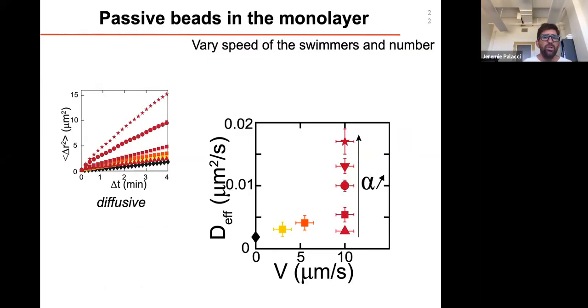So now, taking this mean field approach, we can say, okay, let's forget for a second about the active particles and look at the passive ones. If we look at the displacement of the passive particles as a function of time, we can plot their mean square displacement as a function of time for different conditions. So the black symbols are the thermal case. We see that delta R squared is linear with time. We have a diffusive displacement of the particle, and we can estimate the diffusivity of the 5 micron particle.